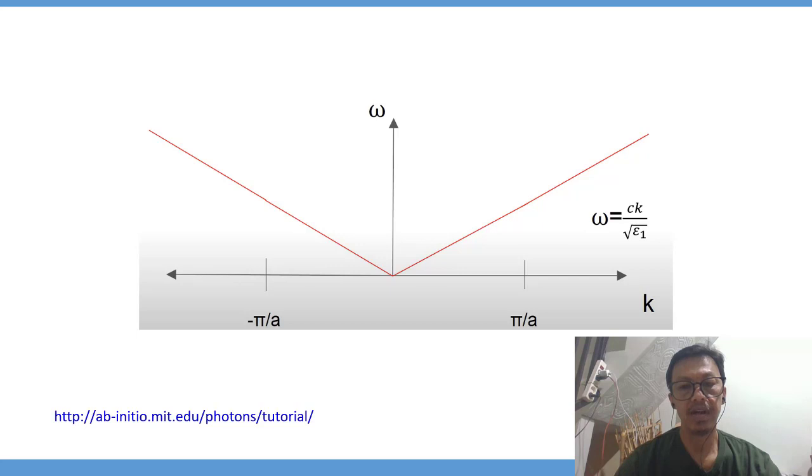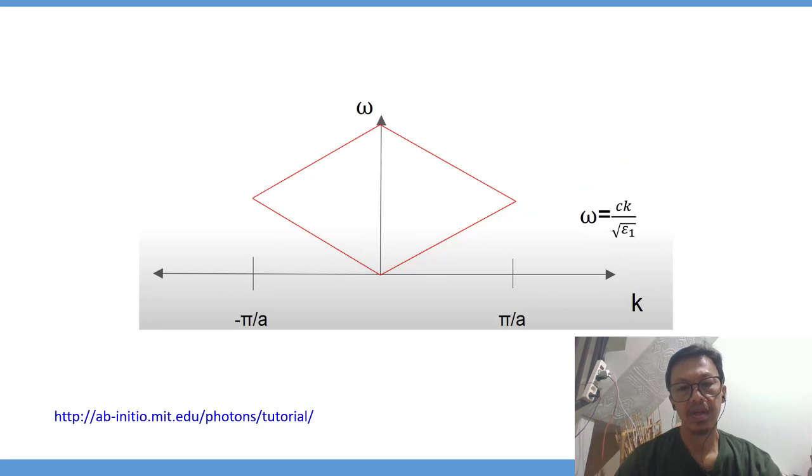We have a graph of wave number versus frequency. For a non-photonic crystal with a uniform medium, by treating it like a periodic medium, we can fold the wave number over at K plus or minus pi over a. With this new folded graph, we can see the point of reflection at K equal pi over a.